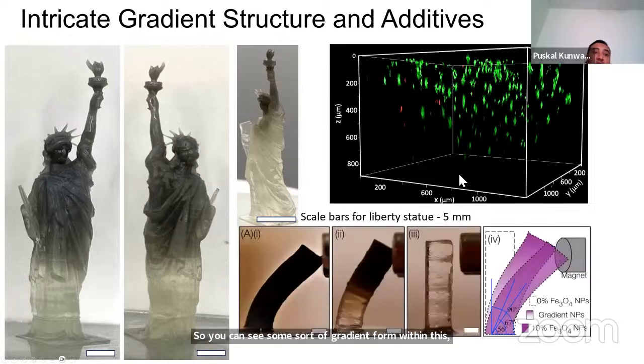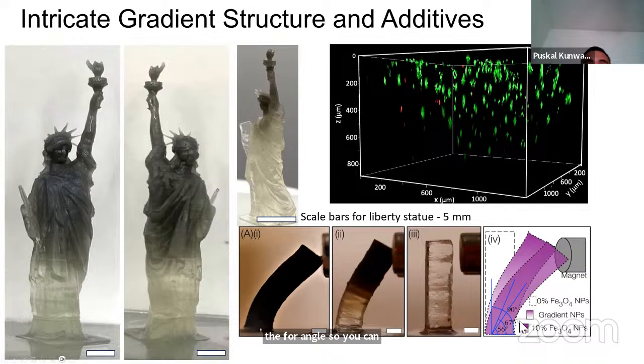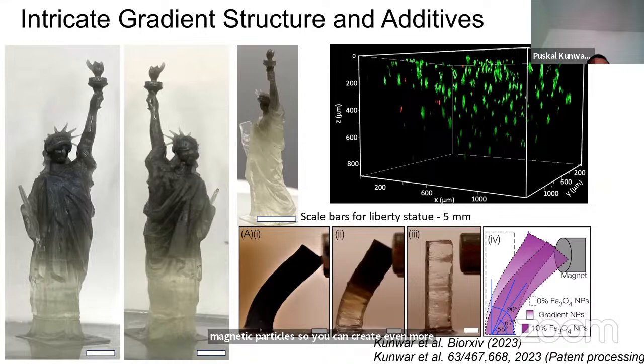Now you could also add some magnetic material in a gradient fashion and see the response. For example, in this one we used 10% Fe3O4 throughout the construct. In the second one we varied the magnetic nanoparticles in a gradient. In the third we did not use anything. We saw the magnetic response in the form of angle, so you can definitely see different magnetic responses based on the distribution of magnetic particles. So you can create even more intricate structures with this approach. This paper is under review in Advanced Materials, and you can already access it on bioRxiv.